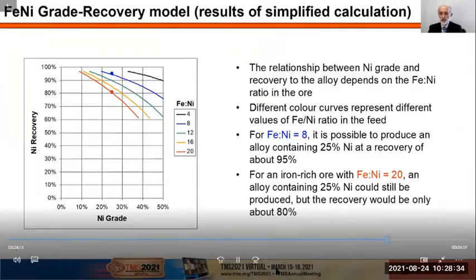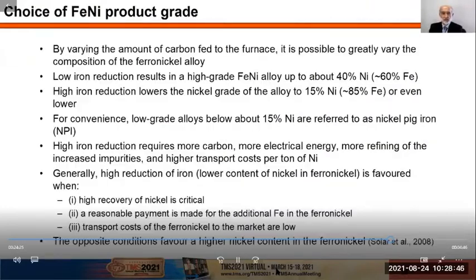But if we were to use an iron-rich ore, say with iron to nickel ratio of 20, an alloy containing 25% nickel could still be produced, but the recovery would be only about 80%. So now we have the tools to enable us to predict what that grade recovery relationship would look like, but it still remains for us to choose what ferronickel product grade we wish to manufacture.